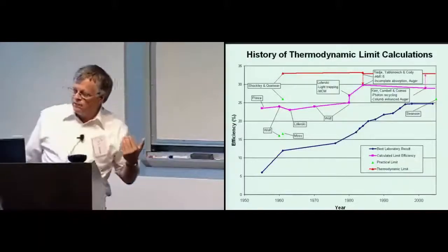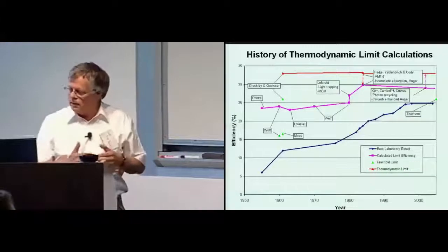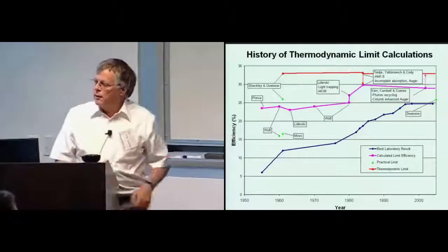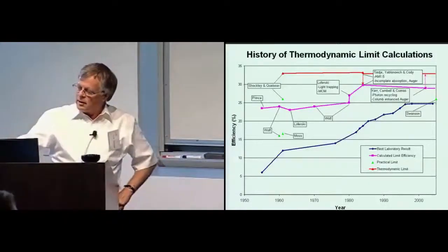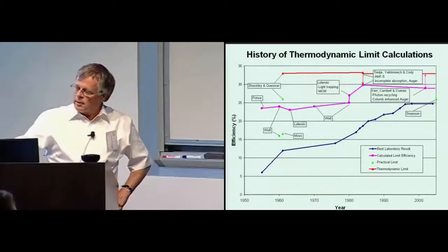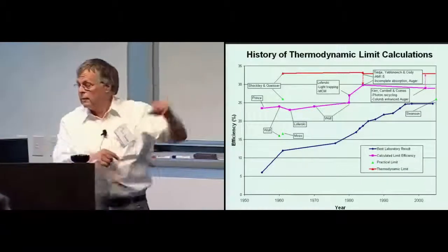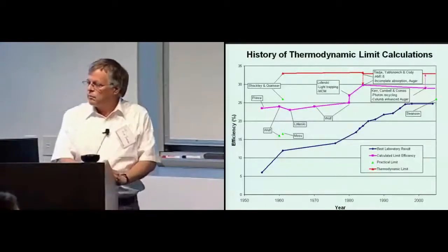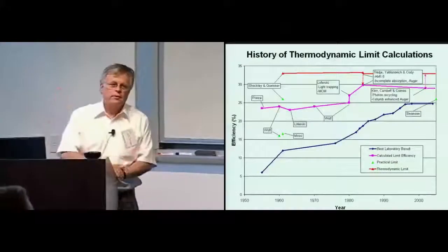So in any case, the analysis following a thermodynamic approach after the Shockley-Queisser, which was also done by Eli, shows that if you take the cell and you add Auger recombination and incomplete absorption, you get the same result as you do with the device model. And if you go out to the far-hand side and eliminate the Auger recombination, it goes right back to the thermodynamic limit.